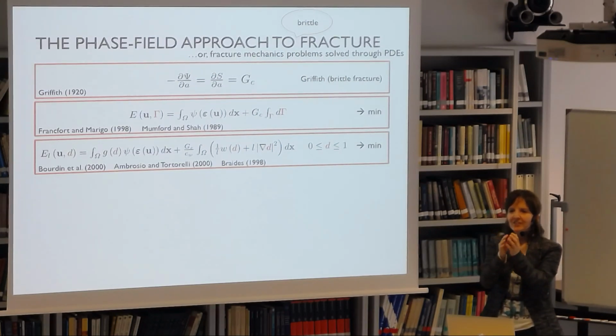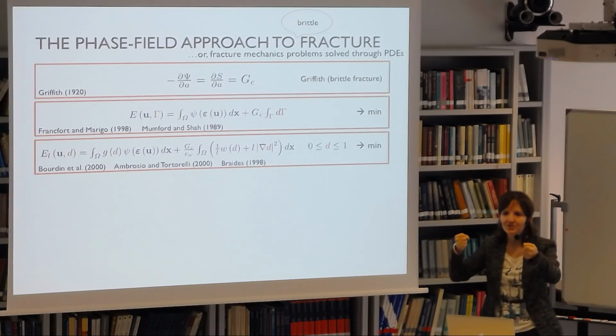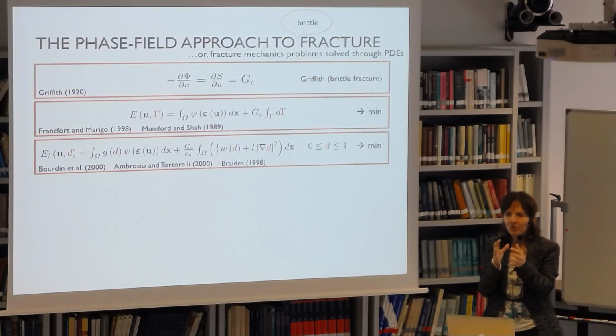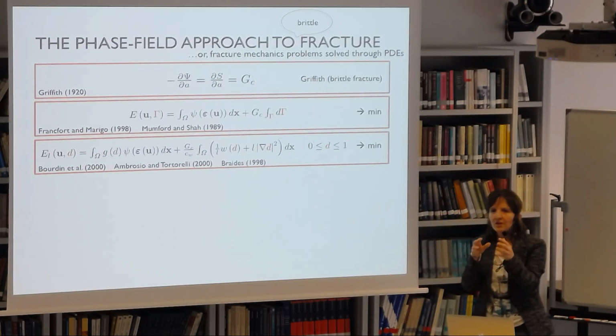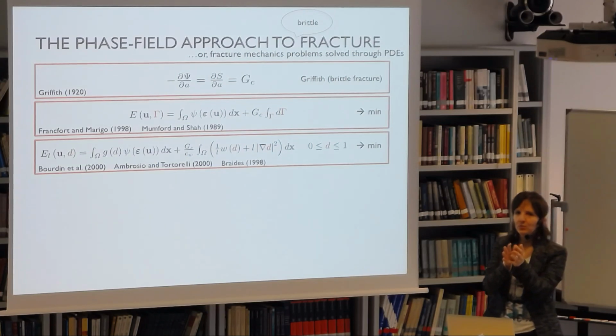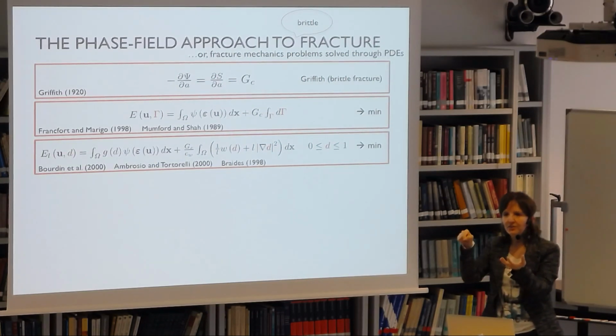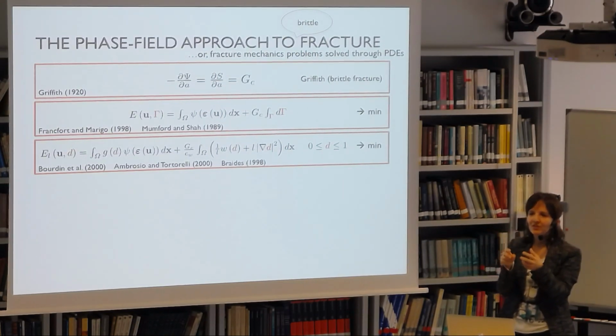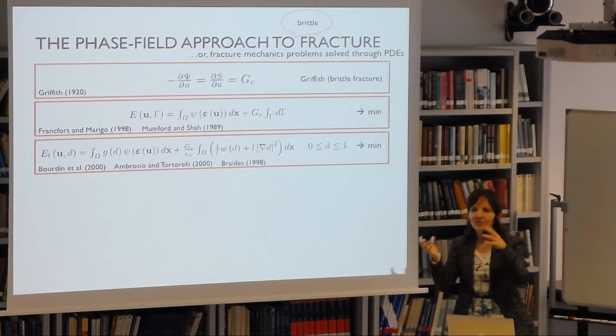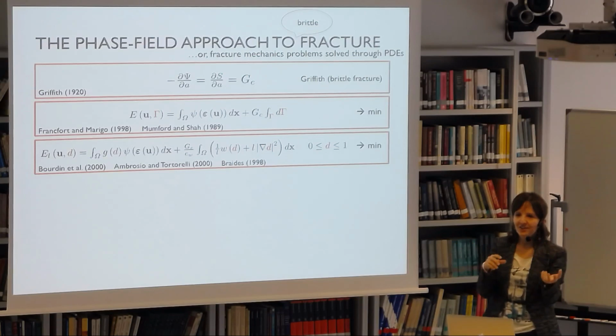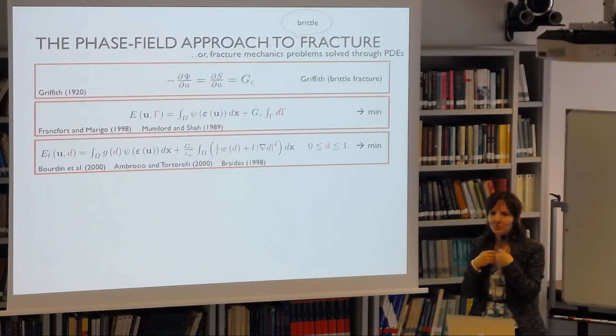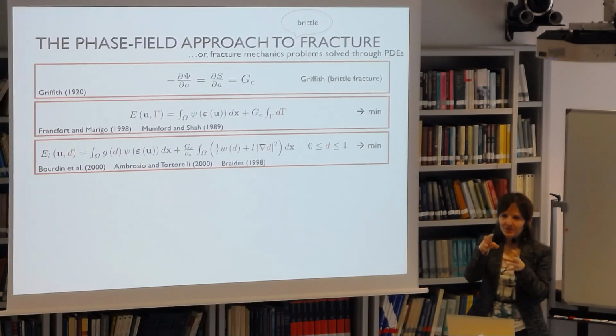And in that case, if you don't have a singularity, you can think of the 1D bar problem, which is a classical problem that you would run in the lab to find out what the tensile strength of your material is. So in my view, in our computations, whenever we have no pre-existing singularity, we tailor L in such a way that we match the critical stress to the tensile strength of the material. Now, the problem is, if you want to use the same L for problems that may or may not have a pre-existing singularity. So the approach, at least what we do, is we calibrate L based on the tensile strength. But then, once we have this L, there are two possibilities.